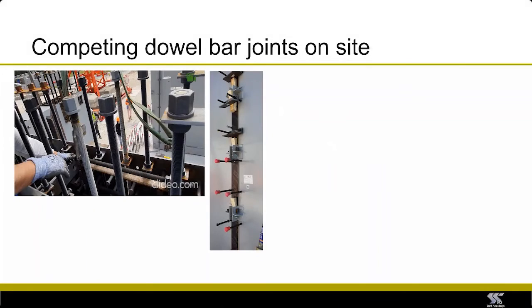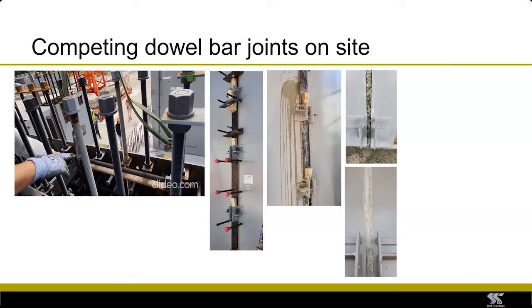Now, for those joints, there is a small gap between modules, so that gap has to be closed in order to do the concreting. And initially, this was done just using conventional formwork at the joint. However, we found that this did not work very well in some places. So where there was leakage of concrete, we ended up with a joint that was of poor quality. Where there was no leakage, the joint was perfectly okay.